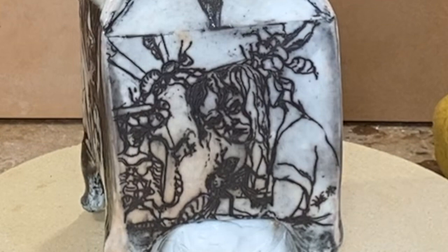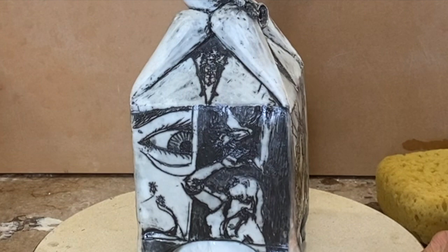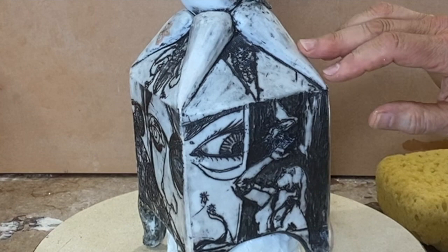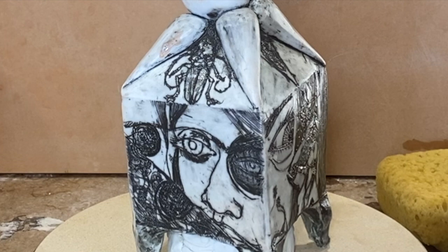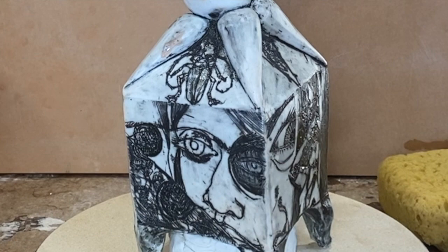The flux in the glaze causes your dark lines, as you see here — they kind of glassy and they come like glazes and they spread out. And so sometimes I have to take a stone, a sharpening stone, and grind away — I did that on the right eye — grind away and open it up again so that you can see the lines, which disappear because the flux comes out and it sort of spreads the black underglaze out, almost like a glaze fuming.